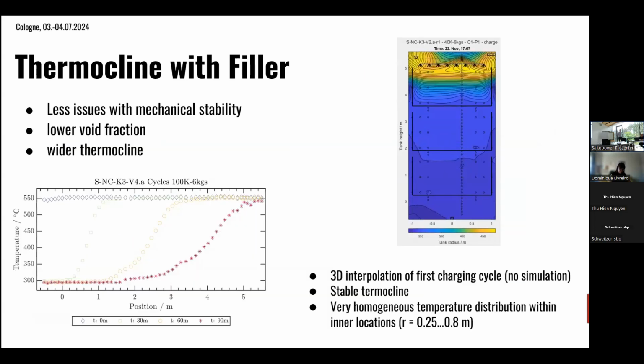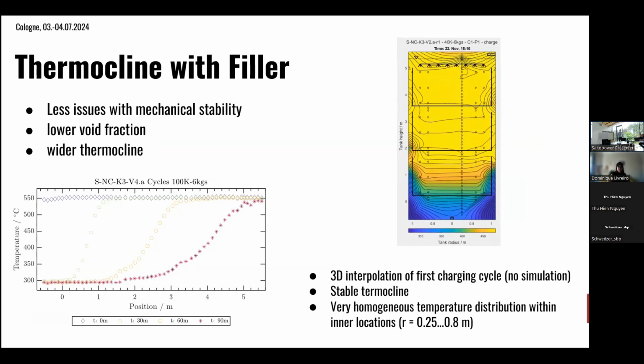And here I also have a nice video of the discharging cycle. You can see here, so that was just the first charging cycle. If you compare it with the other results, the thermocline is getting a bit wider. That is because, particularly in the project, we didn't have the material which was the one we originally designed. It was more something available. But obviously, if you have small rocks and flow around the rocks, then there's much more mixing and a much better heat transfer into the material than if you have straight channels where the flow is going through.